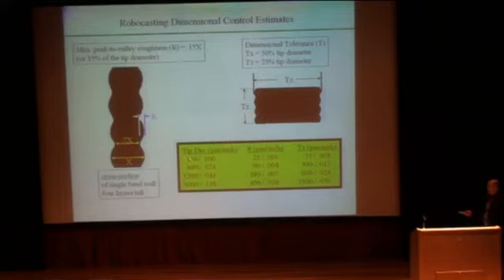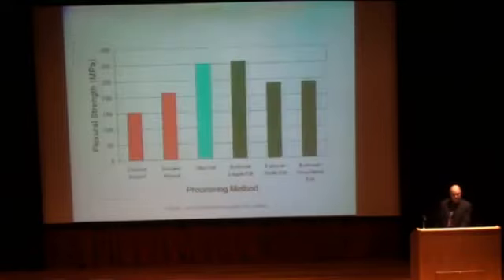get really fine parts, but it will take you forever to build that part at 150 microns at a time. Or if you want to go to a bigger bead and build that part in one swipe, you can do it, but the drawback is going to be a lot of roughness. And similarly, the dimensional tolerance that you have, both in height and width, is going to be related to the size of that bead, which is going to take away from your build speed to try and get something really smooth. So there are some things that it's just not going to be good for.